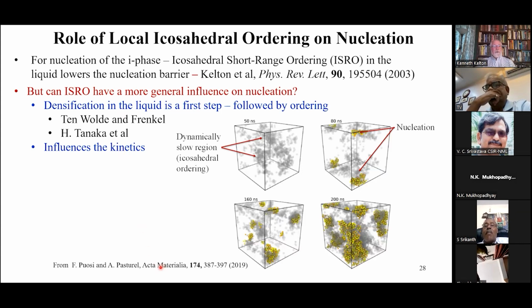This is a recent paper from Pasturel's group in France, where they did MD simulations, and they found that when you get regions of icosahedral order in a liquid, they're slow. What they did was correlate where nucleation occurred, and it always occurred in these slow regions. The other regions are just too dynamic for nucleation to occur. So there's another reason icosahedral order might lead to nucleation and growth. It could be a very complex process with a variety of different reasons.